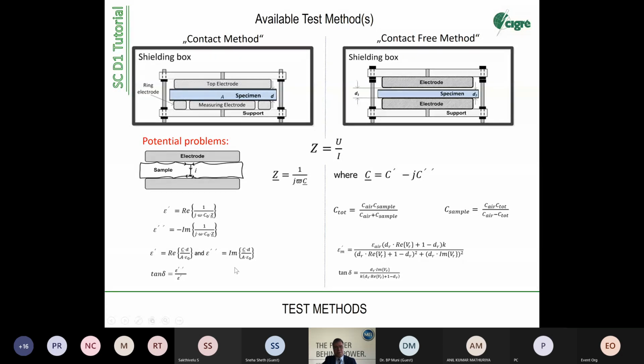So that's easy theory. What are the problems? It's even simpler on the left side, because here you're just working with geometrical factors, so you don't have other disturbing factors. But if you look at practical measurements and practical samples, maybe you're working with silicone rubbers, then it's easy because the electrodes contact your sample smoothly. But if you work with duromer material, or with materials that do not have a smooth surface, then the contact area that you use for the calculations is not the geometrical contact area. It's just the contact area that you get from the sample quality. And this may lead to errors and uncertainties in the results. So we explored both methods, but we selected the right one.